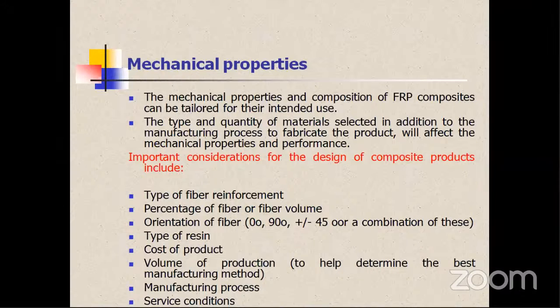As I suggested in classical lamination theory, for the laminates you develop, especially the fabric reinforced composites, orientation of fiber is very, very important. You can orient all fibers in X direction or in Y direction, or it is possible to orient from 0 to 90 or from 90 to 0, that combination. And what type of resin, whether it really has good inherent properties? Is it an effective matrix material for the reinforcement you selected?